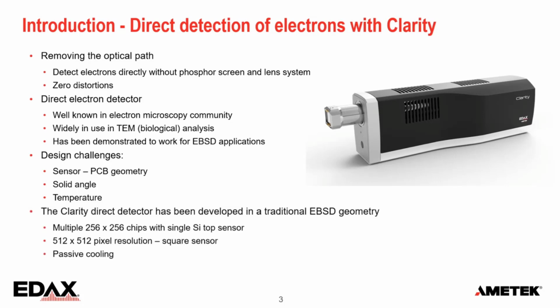Now, for the Clarity, we have developed a system in the traditional geometry. So it's a side-mounted EBSD detector with a tube that you can insert close to your sample. There are multiple chips. It's a 2x2 array with a single Si top sensor. And so effectively it's 512x512 pixels. And from the tube going out, there is a passive cooling system. So we can just let it run for very, very long times. I just collected a scan here for more than 24 hours and that is no problem. Everything is nice and stable.